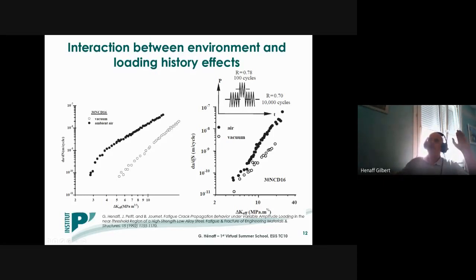Now looking at the fatigue crack growth rates obtained on the same steel under the same environmental conditions, but considering this type of loading pattern, which is constituted of a baseline loading with a load ratio of 0.7, and every 10,000 cycles of this baseline loading, we introduce 100 cycles characterized by a higher mean stress, or a higher load ratio, in that case 0.78.